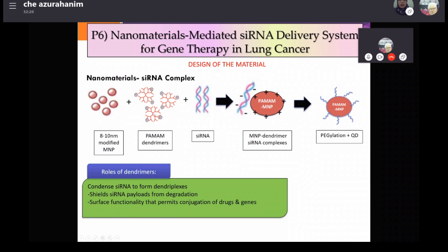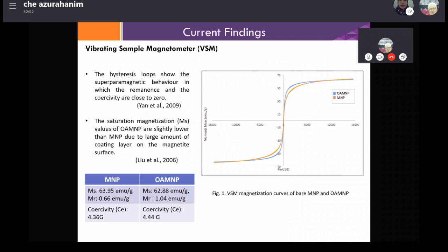The role of the dendrimers used here is to condense the siRNA into the dendriplex, and we hope that the dendrimer can also shield the siRNA payloads from degradation, and provide surface functionality that permits the conjugation of any other anti-cancer drug, as well as any other genes we would like to put in. Similar to the previous study, because we are using magnetic nanoparticles, we did some characterization on VSM, and we found that the magnetic saturation for just MNP is about 63.95, and for OA-MNP is 62.88 emu per g. I think this is at least higher magnetic saturation compared to the first study.